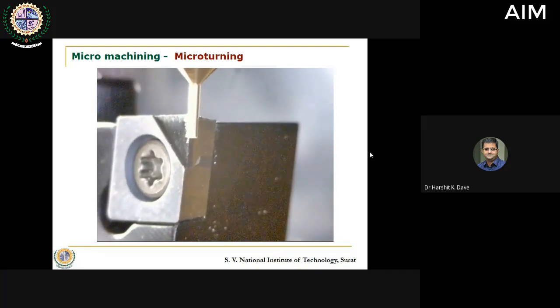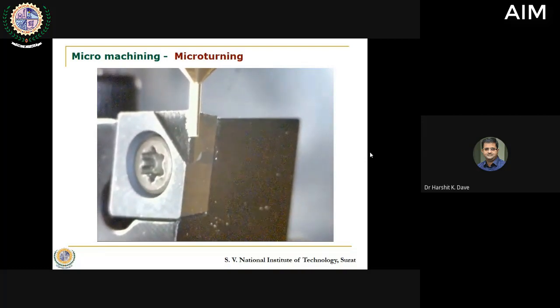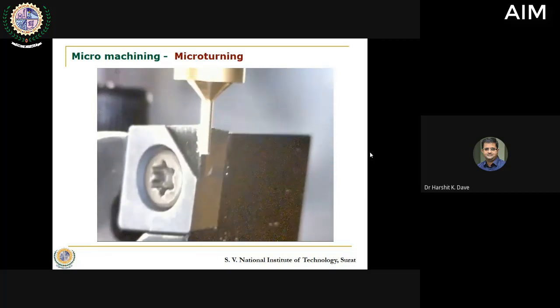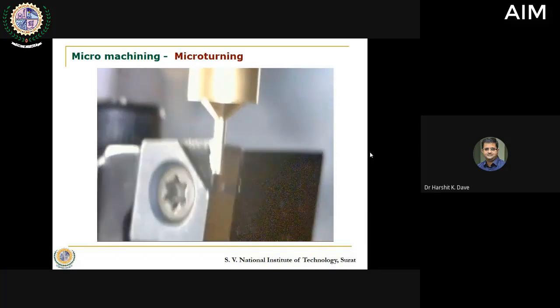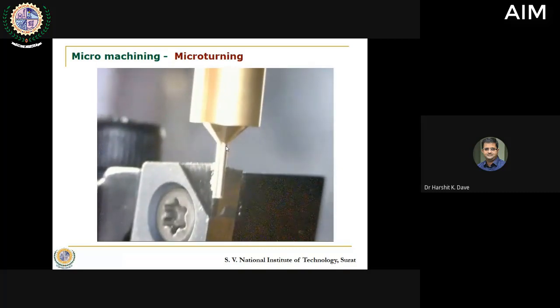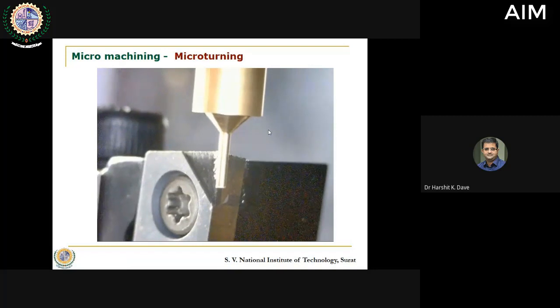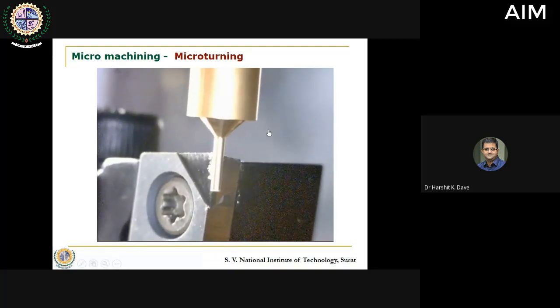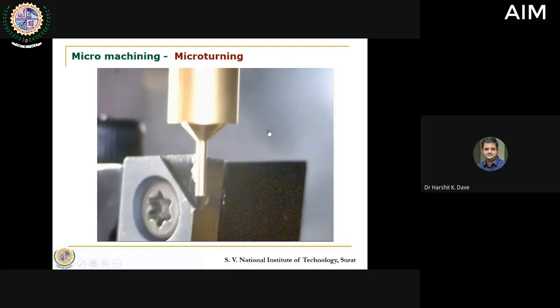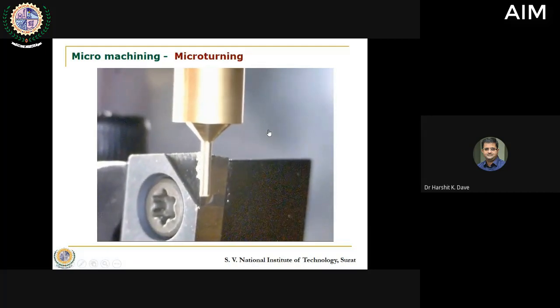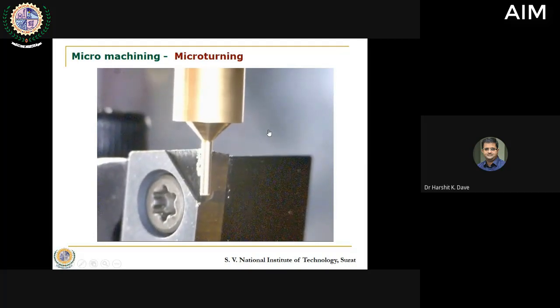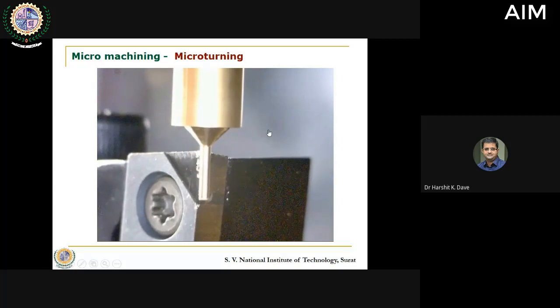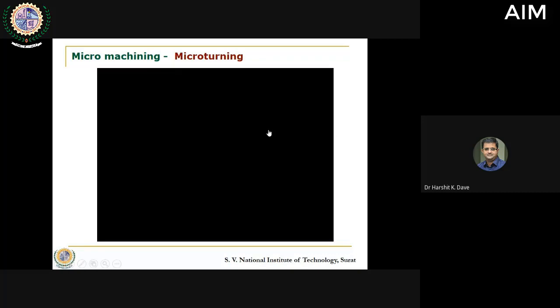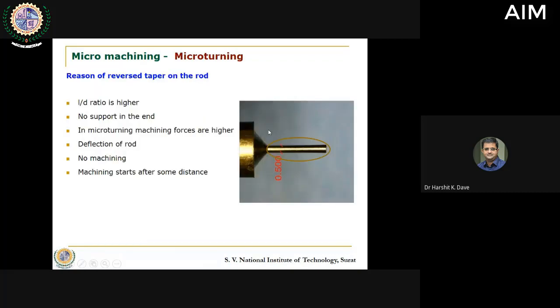But this is one such cut that is being initiated, and eventually up to 5 mm we carried this out. So this entire length that you see over here, from here to here, that length is 0.5 mm. Sorry, 5 mm. And on that 5 mm, we took 0.1 mm of depth of cut and we started machining. And eventually, after every machining, you can assume that in 10 passes, you will reduce 1 mm. So from 1.5, we went to 0.5. So we had to take a large number of cuts. Now we tried and effectively we could produce it.